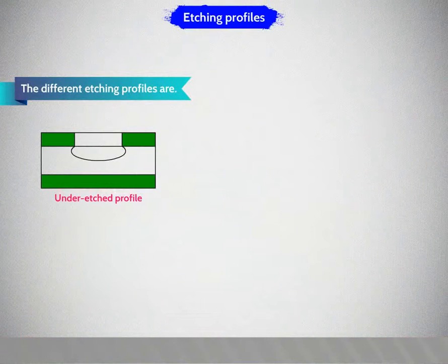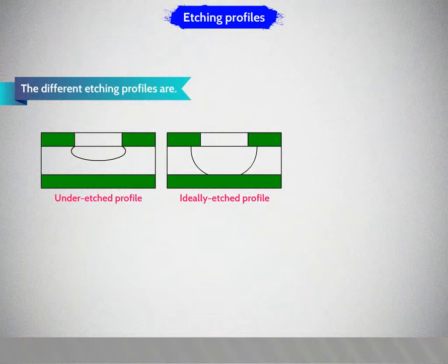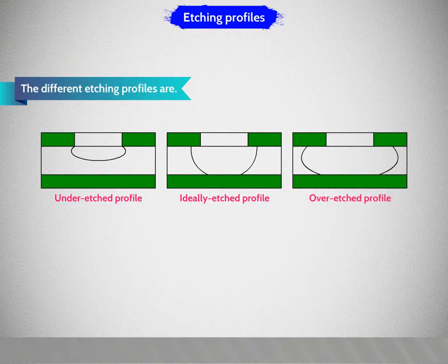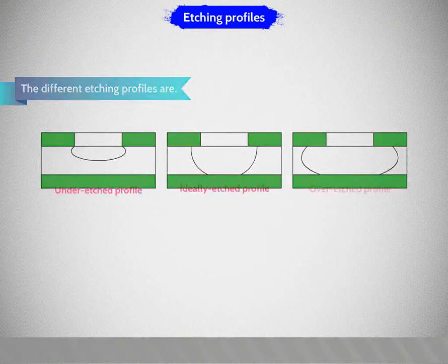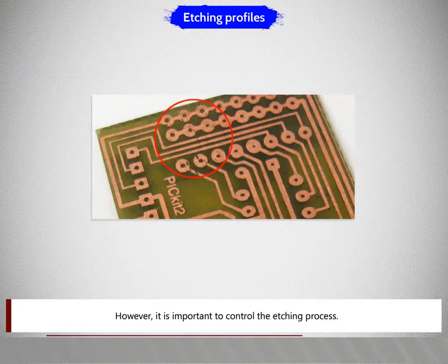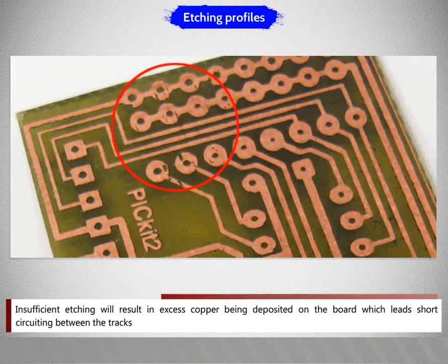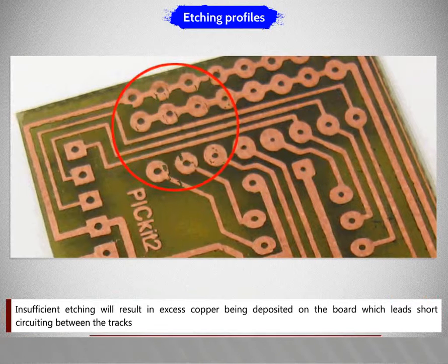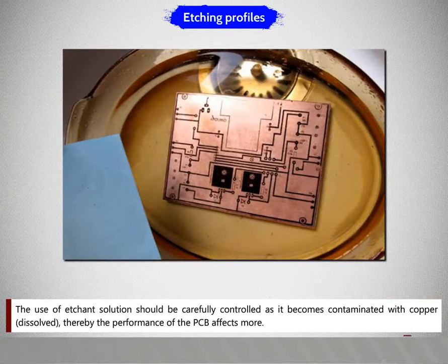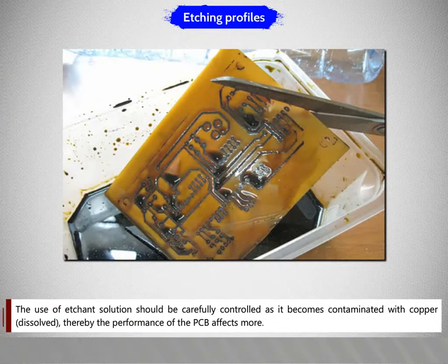Etching profiles: under etched profile, ideally etched profile, over etched profile. This figure shows different etching profiles. However, it is important to control the etching process. Insufficient etching will result in excess copper remaining on the board, which leads to short-circuiting between the tracks. The etchant solution should be carefully controlled as it becomes contaminated with dissolved copper, whereby the performance of the PCB is affected more.